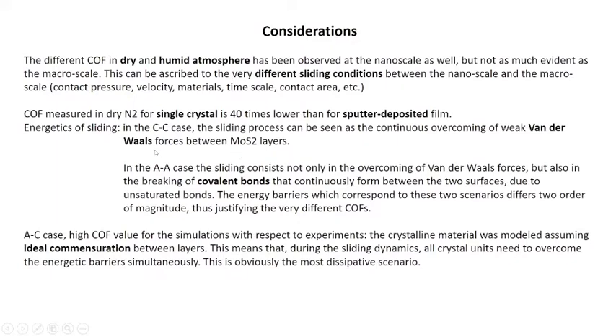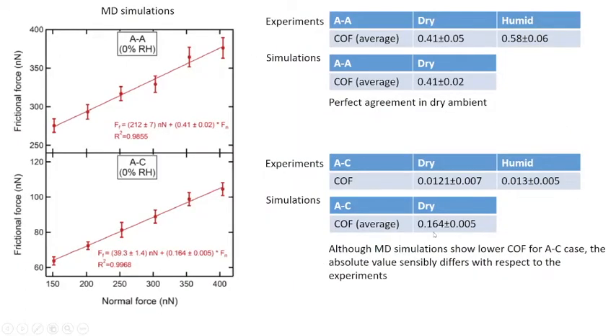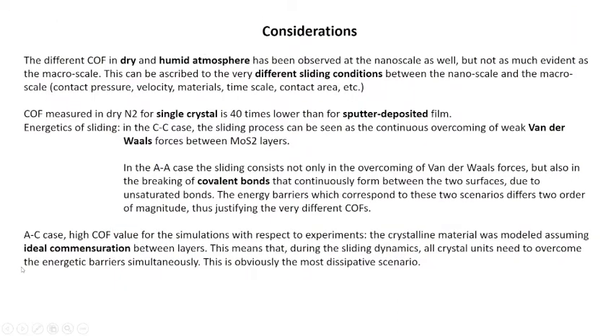And this explains why in this case the coefficient of friction is far lower with respect to the amorphous case, where the sliding does not only involve the overcoming of the van der Waals forces, but is related also to other phenomena such as the breaking of covalent bonds that can form between the surfaces because of the different crystallographic structure. And related to the difference here between this value and this value, this has been ascribed to the fact that in the molecular dynamics simulation, the model assumes that we have commensuration between the sliding planes. So this is the most dissipative scenario, which is not the case of the experiments. We cannot control exactly the orientation of the crystal.